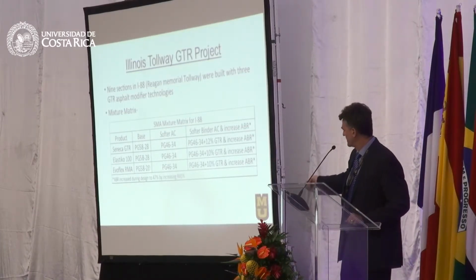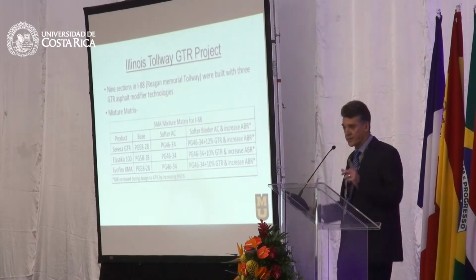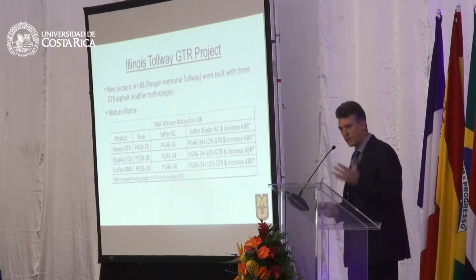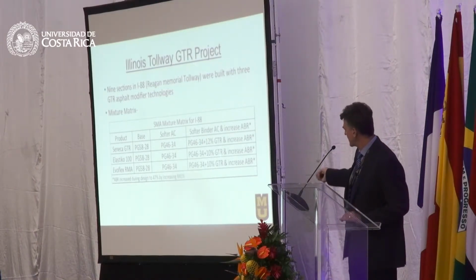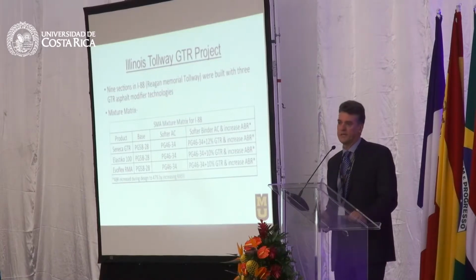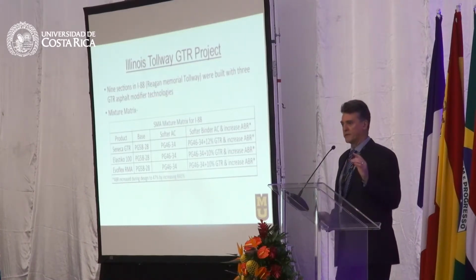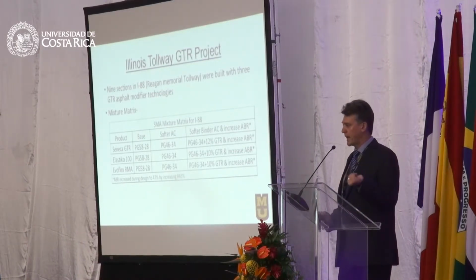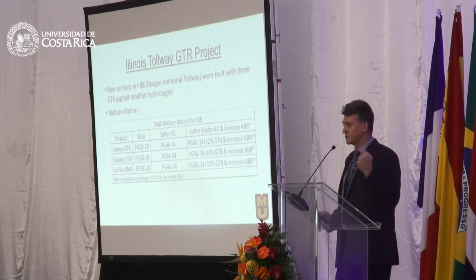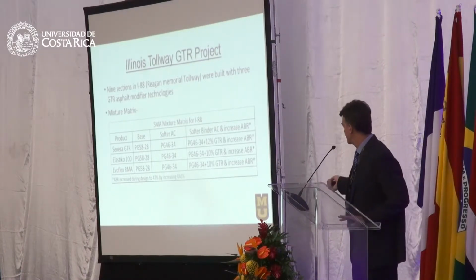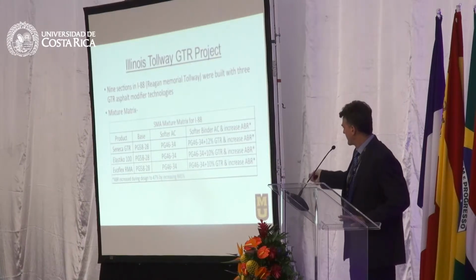So the first 2 columns that you see here have 33% recycling or asphalt binder replacement. The last column here has 47%, and that's done through the use of recycled asphalt concrete, RAP, and recycled asphalt shingles, or RAS, which are very, very stiff. And so that's their 3x3 matrix.